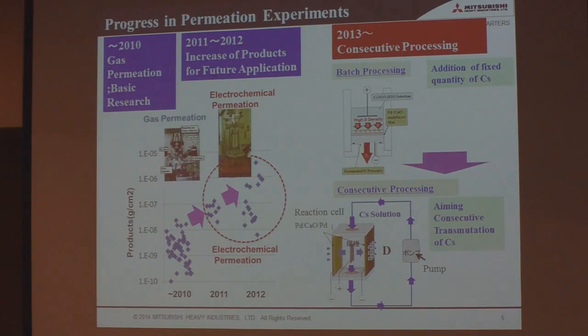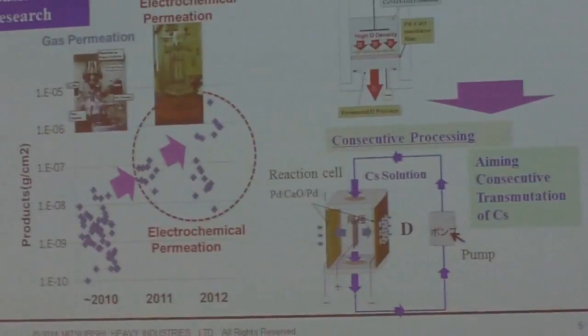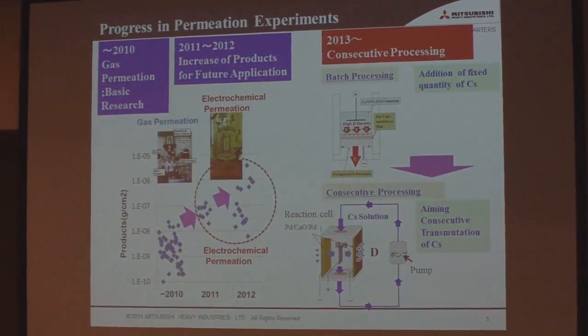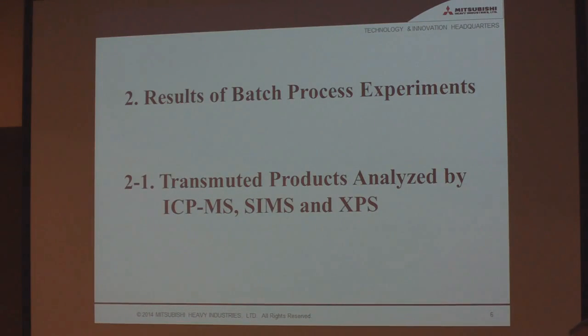Batch processing, as we usually call it: before permeation, we put some cesium. In the gas experiment, we put the cesium on the palladium surface. And in the electrochemical permeation case, we put some fixed quantity of cesium. But for consecutive processing, we are now aiming at consecutive transmutation of cesium using a flowing, circulating electrolyte. We are now aiming at this kind of process. So first we present the batch process experiment results.